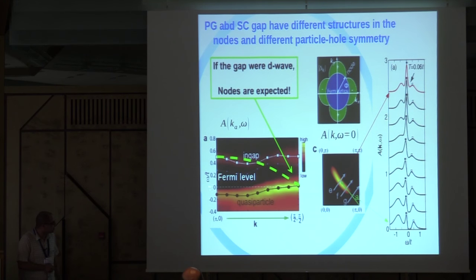Also notice here that the gap is rather asymmetric. Now here it's very exaggerated with respect to reality, but a superconducting gap is particle-hole symmetric. You will have a band here, the first Bogoliubov band, and the band negative. And the minimum should be more or less in the middle. Here the minimum is clearly shifted up to positive energy. So the total gap is asymmetric. So the two don't look to be the same.